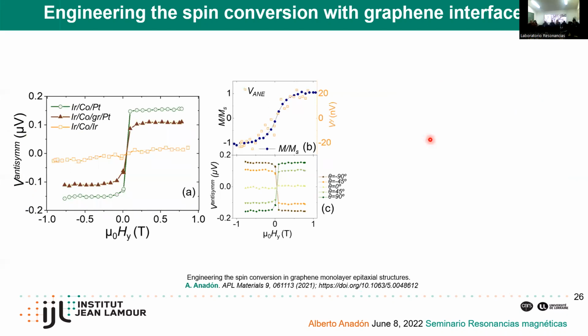So now let's move to the measurements in thermospin. Here I'm showing the comparison between an iridium cobalt iridium. So in this system, basically we are seeing mostly the anomalous Nernst effect, and in here we are comparing the other two samples that I just said: iridium cobalt platinum and iridium cobalt graphene platinum.